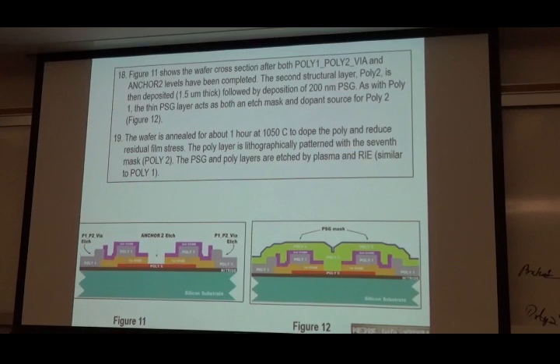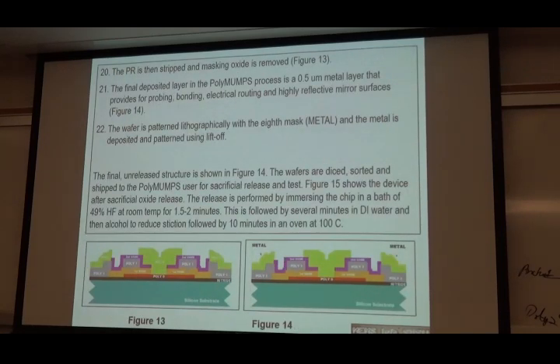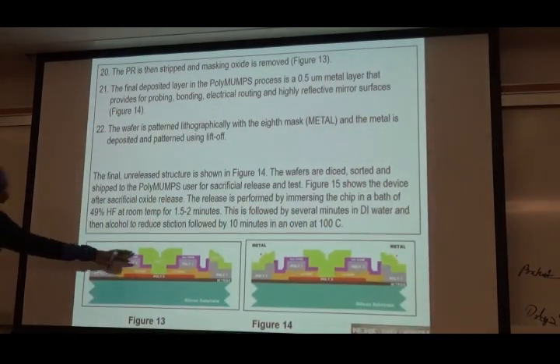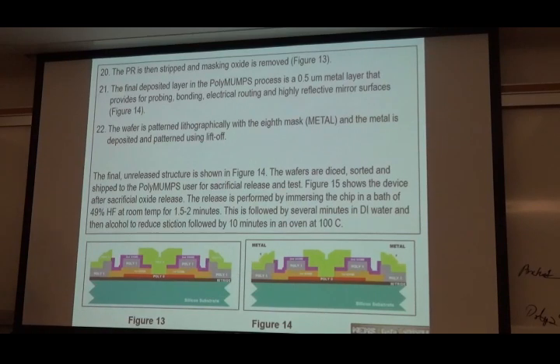That's what you see, the dot, the loop. Once you do the PSG, you do lithography, and then you're able to pattern. Okay, now we're almost there. Poly 2 is patterned. At this point, I have my poly 2. The only thing remaining is the metal layer. I do metal deposition.